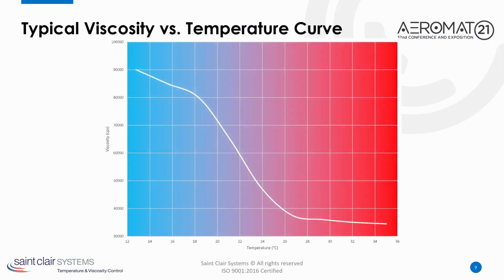Here's a viscosity versus temperature curve for a typical sealer or adhesive. While paint curves generally run in the range of 50 to 350 centipoise, sealers and adhesives run orders of magnitude higher, often falling into the range from 30,000 to more than 1 million centipoise. But what's really important about this curve is the steep portion of the curve from 18 to 26 C. That's about 67 to 78 degrees Fahrenheit. So it's right in the middle of the ambient range.